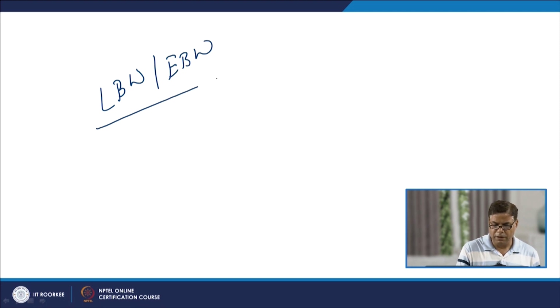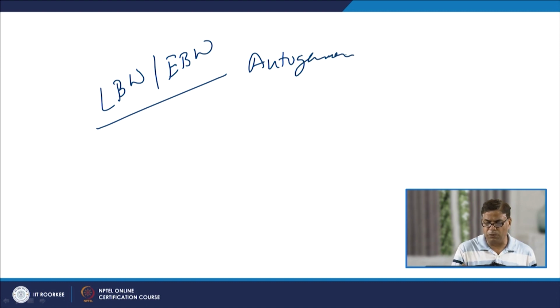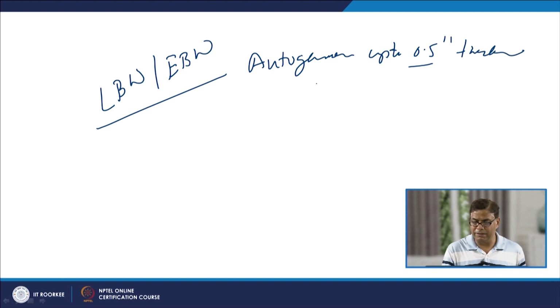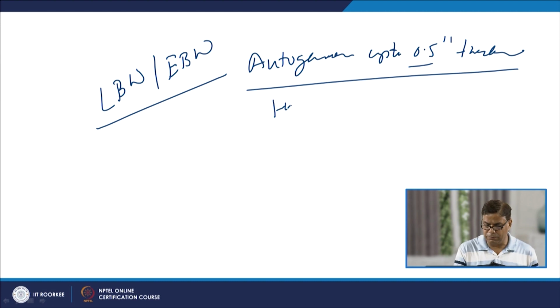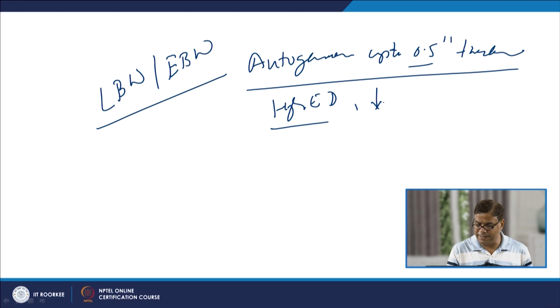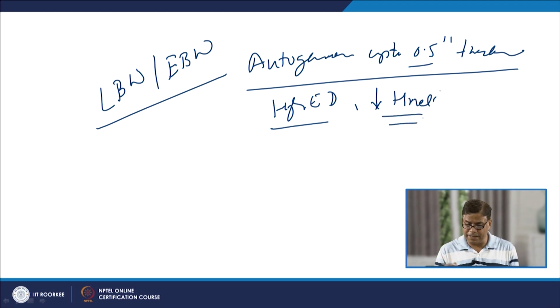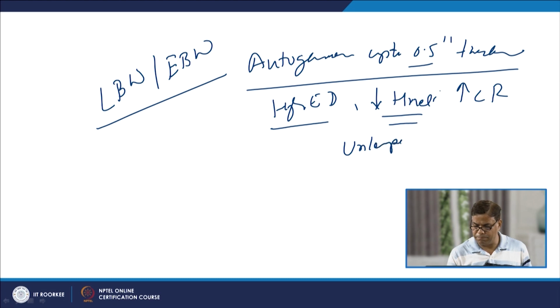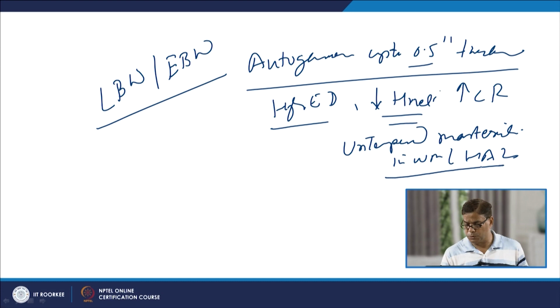We can use laser beam welding and electron beam welding for autogenous welding, meaning direct welding with no filler, up to 0.5 inch thickness of the Q&T steels. Since both these processes are of very high energy density, they supply very little heat for realizing the fusion of the faying surfaces to develop the joint. Cooling rate is extremely high, and because of the high cooling rate, mostly with these processes we get untempered martensite both in the weld metal as well as the heat affected zone. So, we need to be careful about the embrittlement associated with the untempered martensite.